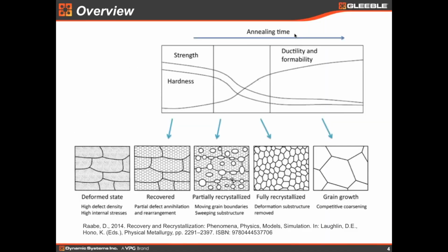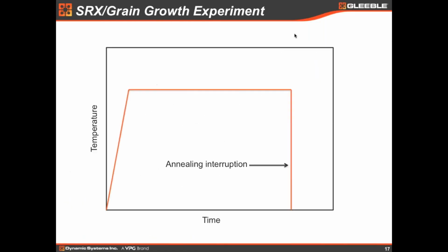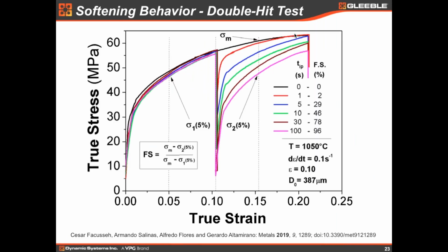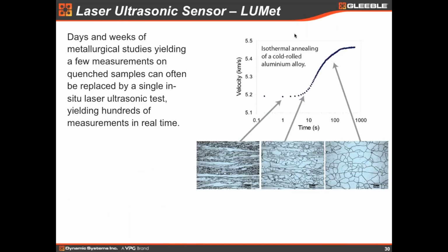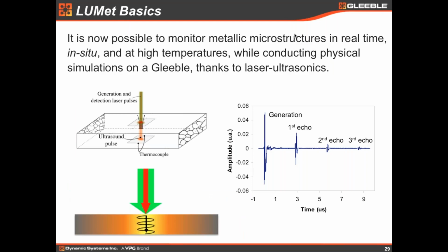Sure. Okay, absolutely. So the Lumet works by measuring two things in the material. It measures the speed of sound in the material, and the speed of sound is calculated by the space between the echoes. So we know the dimensions of the sample, and we know the time it takes for that shockwave pulse to go through the sample, echo off the back of the sample and come back to the surface. So that tells us the speed of sound in the material. Now, it turns out that the speed of sound gives us a lot of very useful information. The speed of sound is directly related to the bulk modulus of the sample, so you can certainly measure that.